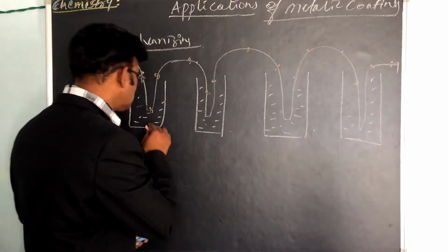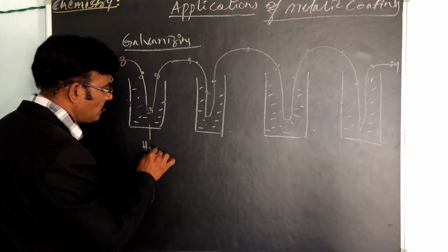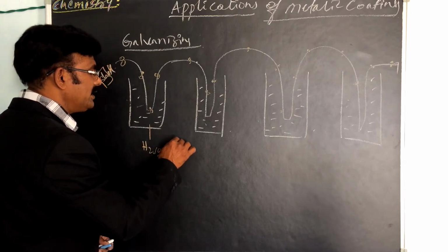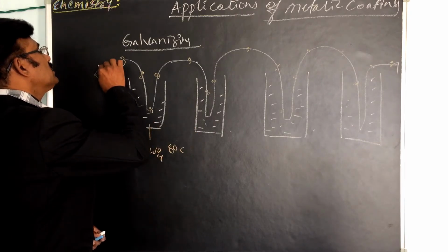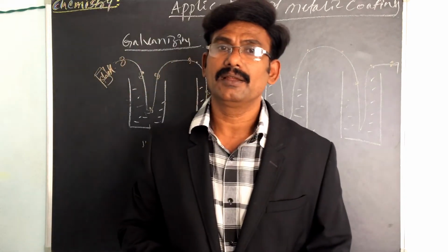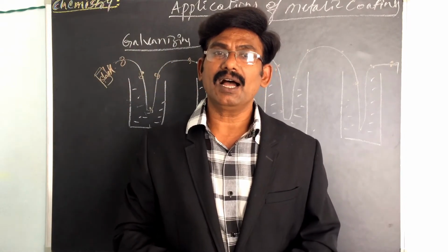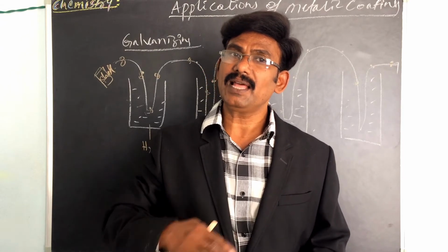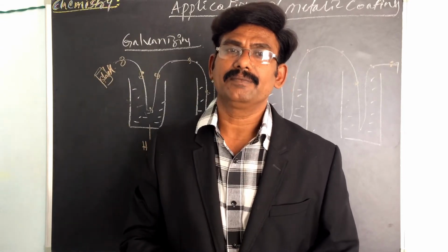In this solution H2SO4 is there, at 80 degrees centigrade temperature. The metal sheet should be dipped in a hot sulfuric acid solution. This is the cleaning of the metal.